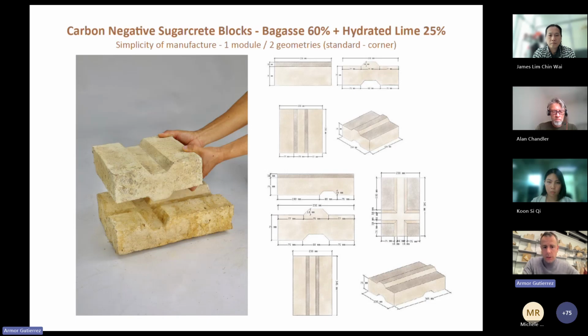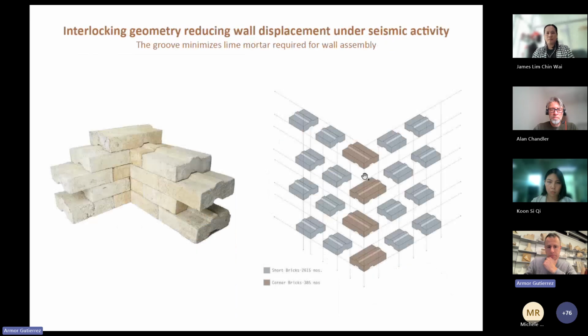We developed two blocks, one that was equivalent to 2 bricks, which is the one that you see at the top, which was 230 times 230 times 75, and then a corner block that allowed us to turn around without cutting or generating any waste on the blocks, which was the equivalent to 3 different bricks. We tested the corner, so this is what we built with the students at the University of East London, and then we built a set of drawings as a guidance on how these blocks could be implemented into a larger wall,